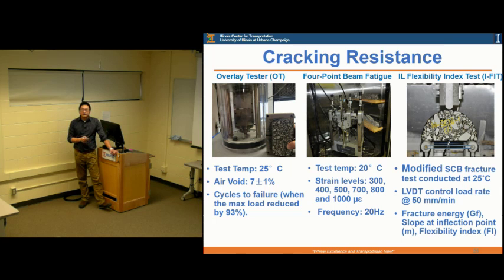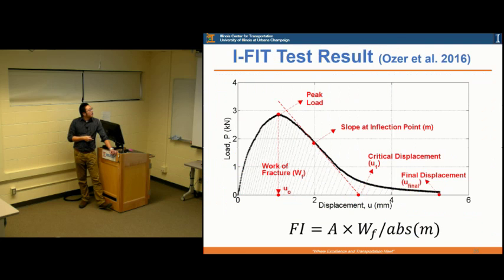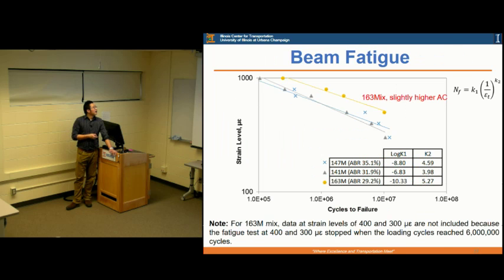The I-FIT test is a little bit different. It's not like a fatigue test, it's monotonic—you just break the sample with sudden loading, and you end up getting a fracture energy and also a flexibility index as your cracking resistance parameter. This is a typical result from I-FIT: you get the fracture work, the energy, and also the M value. It's a combined parameter trying to look at the flexibility of the material, how flexible it is to resist cracking. We also have beam fatigue results here—if you look at the yellow dot, that's the 163 mix.